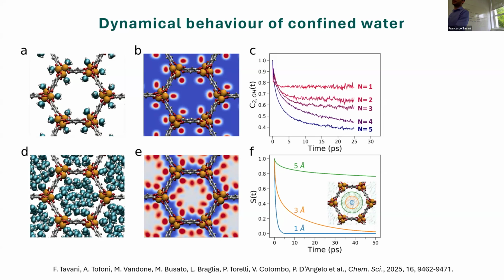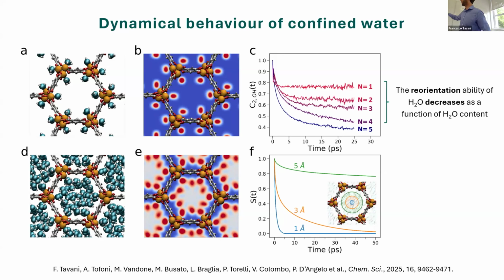So this is basically a function that captures the ability of water to reorient. The faster it decays, the faster it reorients. The slower it decays, the slower water molecules reorient on average. And we find, consistently with previous results, that as the water amount in the MOF increases, the ability of water to reorient decreases. This is due to the increase in hydrogen bonding, which slows down the reorientational ability. And also, of course, the translational properties of water are affected.